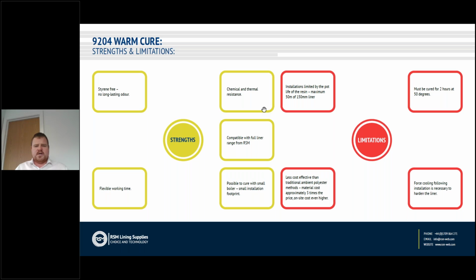So if we consider the strengths or the pros and cons of the 9204 again, as I say, it's compatible with a full range of liners, good chemical and thermal resistance. We can get thermal resistance between 60 and 70 degrees with the 9204 if we post-cure for an extended period of time. We get nice flexible working time. And what's great about our epoxy range is it comes in 2 pre-measured components. So even if you're impregnating on site, you at least have complete control of the resin mix.